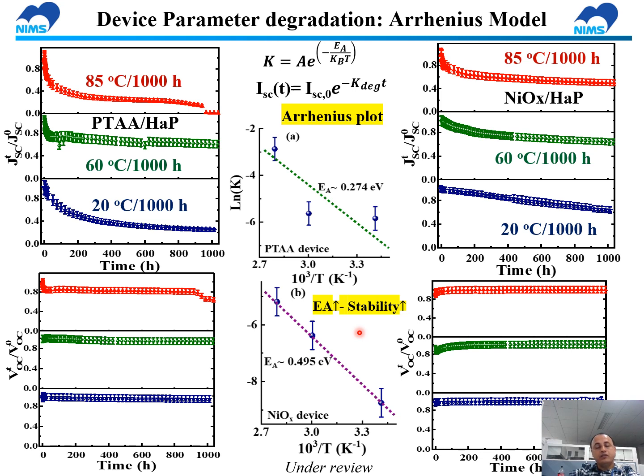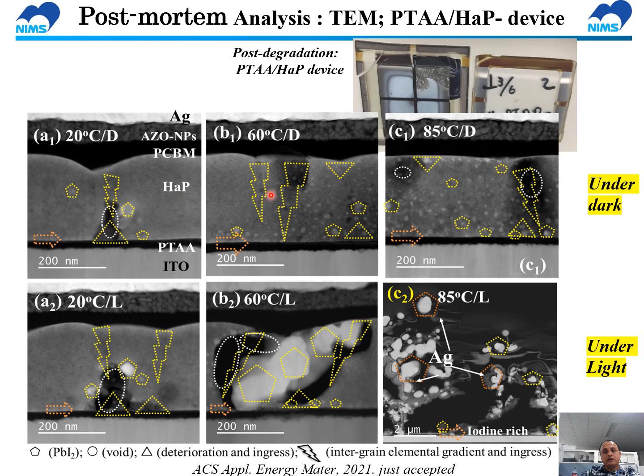And to have more insight, we also performed the post-mortem analysis of those devices by analyzing TEM results. These are the perovskite device with PTAA placed under dark, and these are images of the perovskite device with PTAA placed under light and under different thermal stress. We can see this notation corresponds to PbI2 and void formation, deterioration and ingress at the interface. And we can see, in the cross-sectional image, the device placed under light illumination degrades much faster, and it is much more deteriorated, which leads to poor device performance with aging.